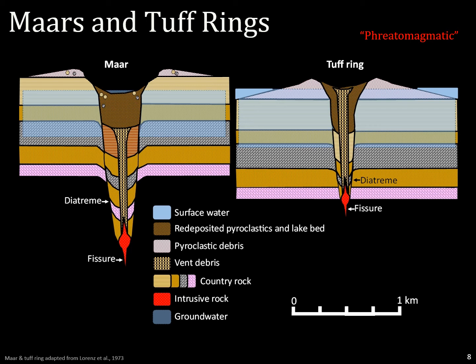Now, glass is what we get when we don't let crystals nucleate as a rock cools. So it's amorphous, it doesn't have a long-range crystal structure, and efficiency refers to how fine the particles are that are produced by the eruption. And when they get rapidly quenched like this, super cooled, you're going to get a very efficient eruption producing a lot of ash particles that are very small.